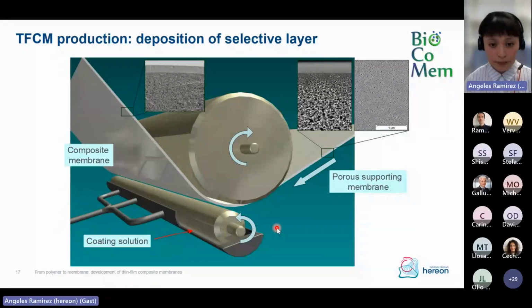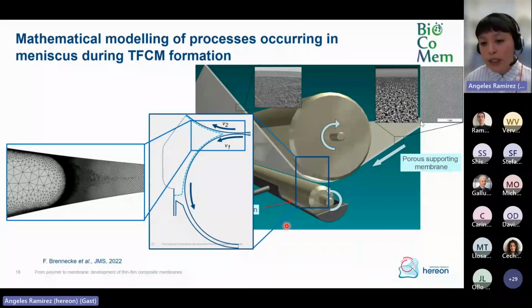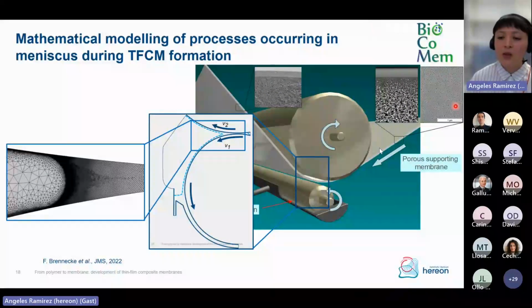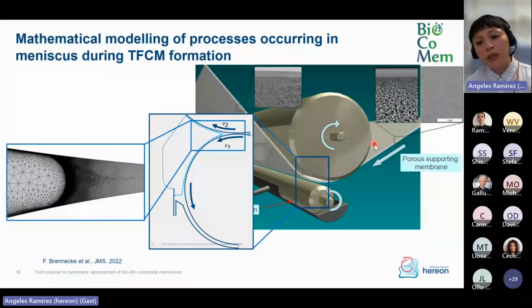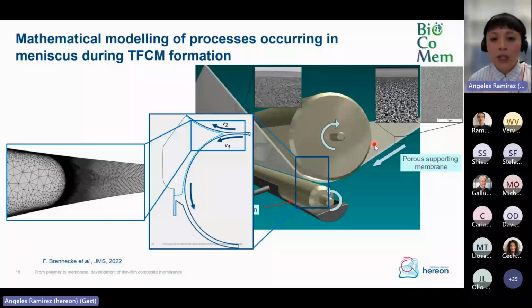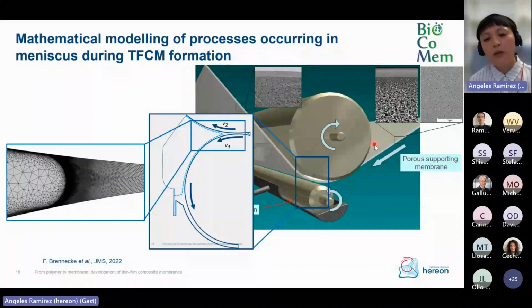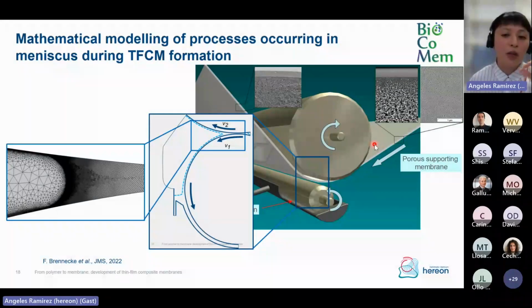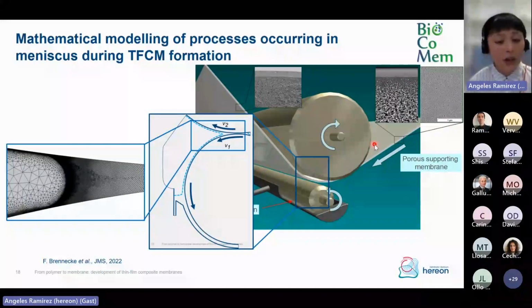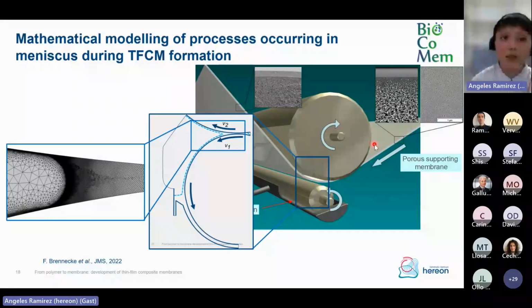If you can see here on the next image, we see this small gap here, my pointer is a little bit slow, sorry. This meniscus is making the solution have a very small contact surface with the porous support, and as the membrane is drawn out by means of the roll, we have continuous evaporation of the solvent. We have to say here that the coating solution is very diluted. This allows us to get a very thin layer of polymer on top of the support that is under 100 nanometers. It is also important to say that we have mathematical modelings describing all this process in detail for those who are interested.